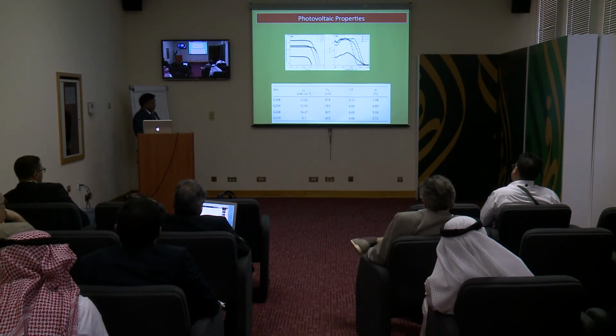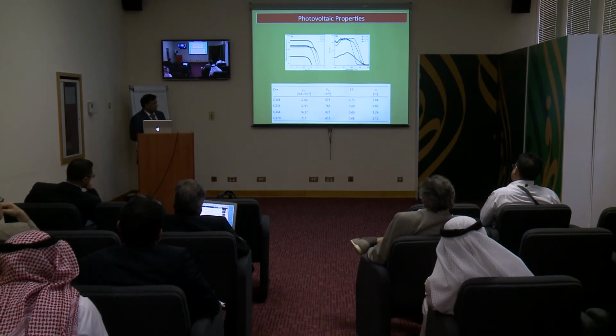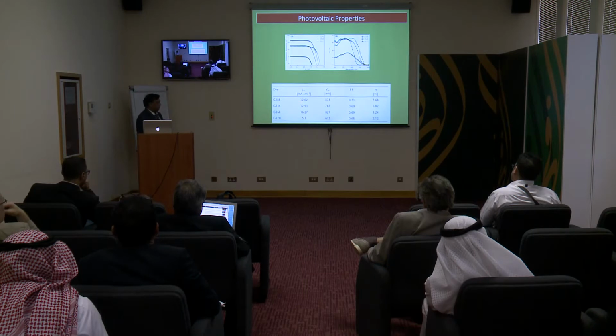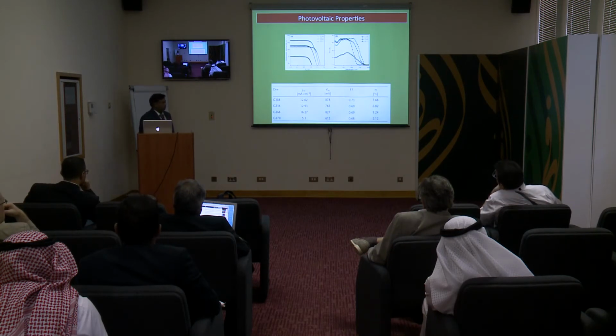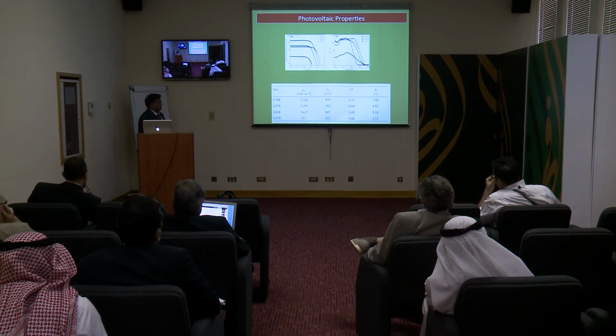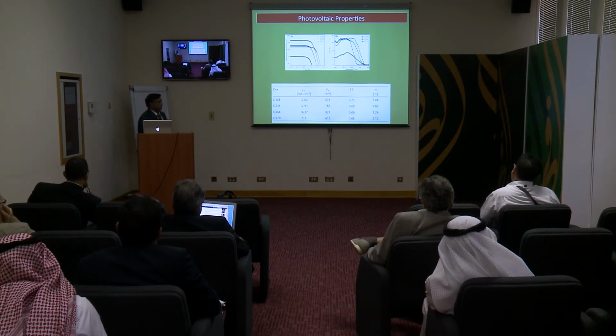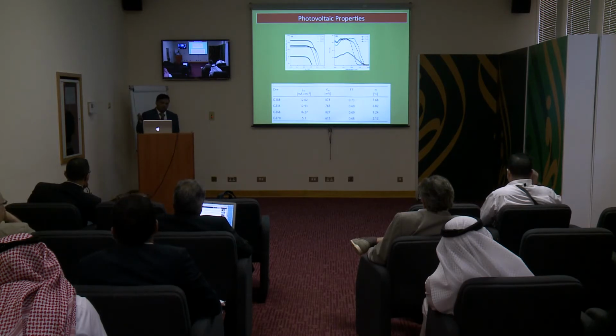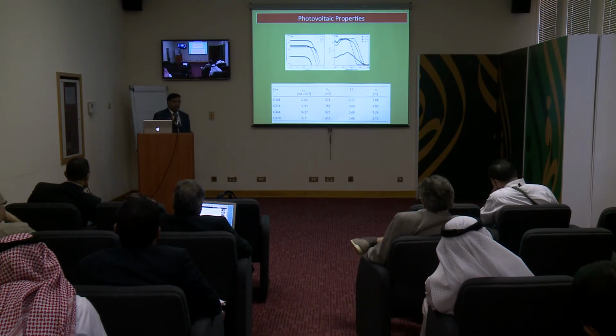To analyze these differences, we also did transient measurements, and we came to know that in the case of this one, the conduction band shift is moving down because of the dipole of the molecule, which contributes to the lower VOC. Whereas in the case of 268, even though there is a small shift there, a huge increase in the current density compensates the performance. So that's why it is still the highest when compared to the unsubstituted. This shows that by systematic tuning, one can find the right suitable pi conjugated system to get high performance.